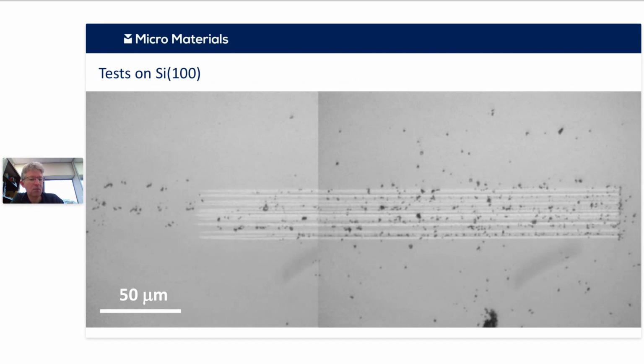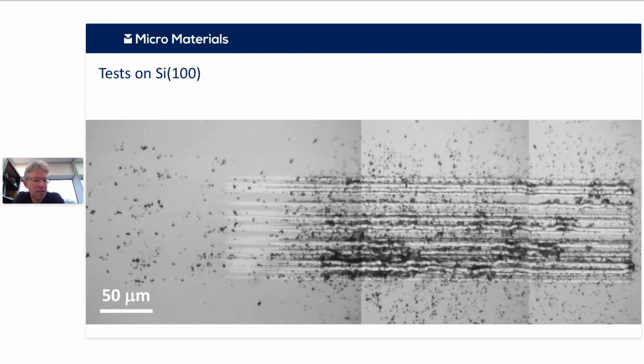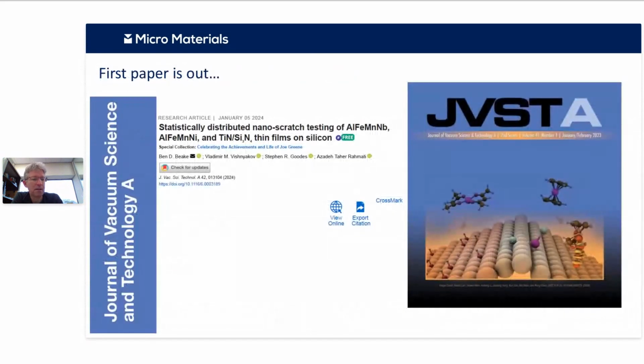If you run that test or do it in more severe conditions, in this case it's higher load, more passes, and here you can see transitions in certain areas to much more extreme damage modes. There's a lot more of this brittle debris, and you're even getting, in this case, lateral cracking in the silicon. So that's quite a severe test.